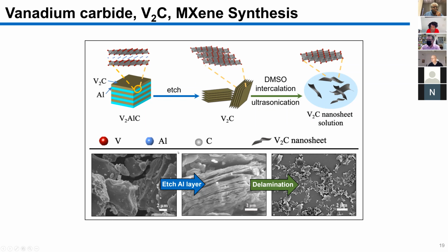More immediately, our group is trying to find a way to remove the aluminum layer without having to use hydrofluoric acid. In a lot of material science work where you need to clean silicon wafers or other surfaces for different electronic applications, it's very common to use hydrofluoric acid. But for environmental applications, especially water treatment, we want to get away from using hydrofluoric acid. It's pretty scary to use in a lab. So we are also actively looking into new ways to more safely generate the vanadium carbide material. Okay.